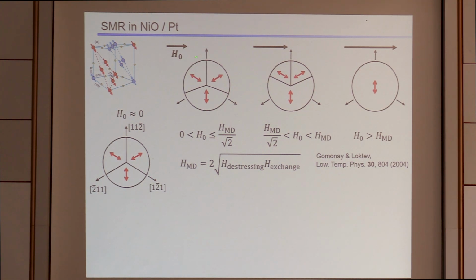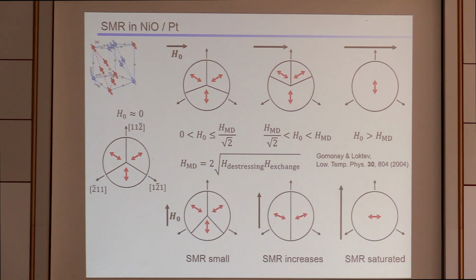If you start with antiferromagnetic domains like this and apply external fields, then gradually these domains will be removed until you reach this fully polarized state, which looks like a spin-flopped configuration. And the magnetoelastic stress in the sample acts as a counterforce, a counterbalance, which prevents this domain reconfiguration from happening at low magnetic fields.